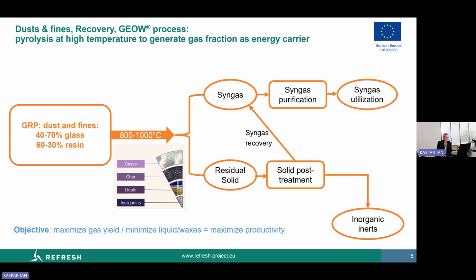We can work in this range of temperature between 800 and 1,000 degrees. And the main product which we want to produce is the syngas, which eventually can be purified and used as a syngas, or even simply by burning and using it for heating or for energy, for electricity generation. The residual solid, of course, might be post-treated because normally we have gases, char, liquids, and inorganics, which are produced by a pyrolysis process.